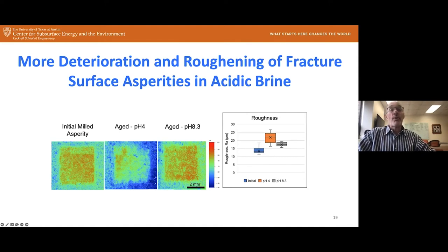We could quantify the roughness from these laser profilometry images, and we see that the roughness at the end of the experiment that was subject to the lower pH conditions was greater than at the higher pH, compared to the initial conditions before the experiment began. So we're getting more degradation of those asperities where the contact is held between those two core halves.